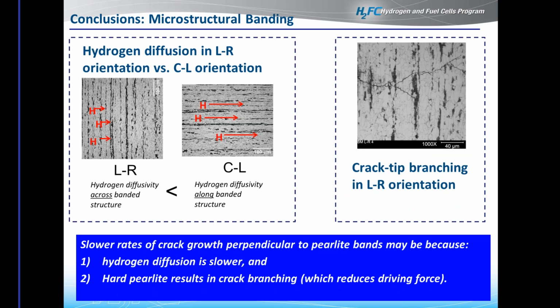And the way we have tried to understand this is that there are two parts that really have to happen in order for hydrogen embrittlement to occur in this situation. We need to have a sufficient supply of hydrogen, and we need to have a sufficient driving force. This first box on the left shows that the hydrogen in the LR orientation must diffuse through regions of alternating ferrite and pearlite. The diffusivity in pearlite is lower than in ferrite, so overall the effective diffusivity is going to be reduced if we're trying to move hydrogen in this direction, because this is the way the crack tip would be propagating through, so we need to get the hydrogen ahead of that crack tip. Now contrast that with the CL orientation, in which we have these short circuit pathways for the hydrogen to diffuse through the ferrite, and hydrogen therefore is going to be able to move through there much more quickly, and therefore we won't have a hydrogen supply issue.